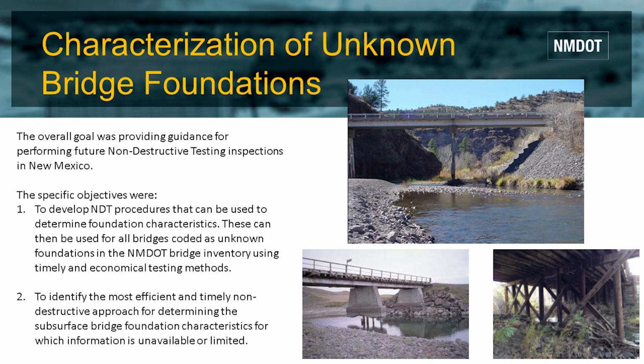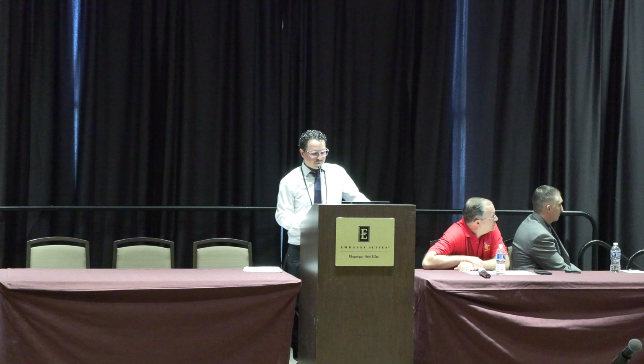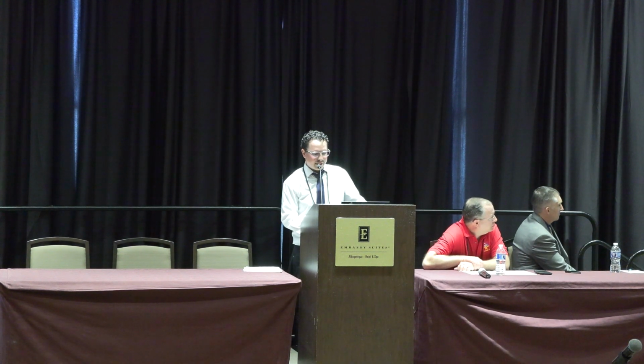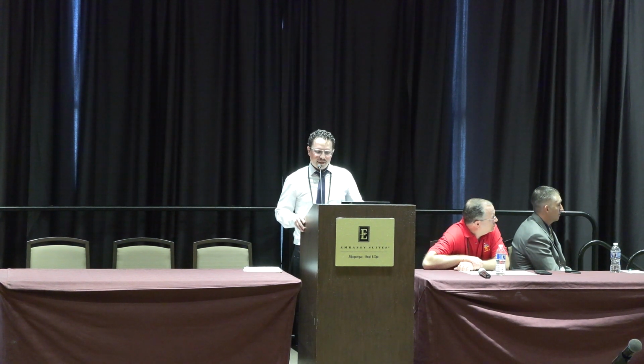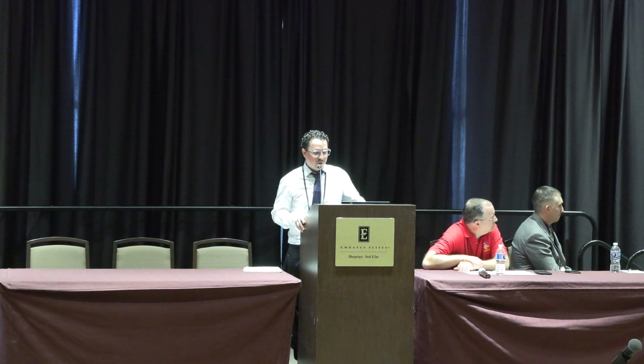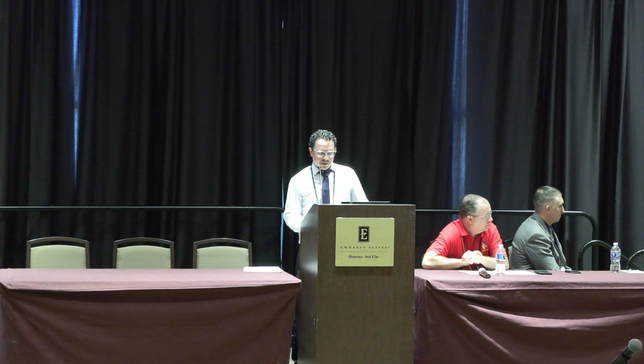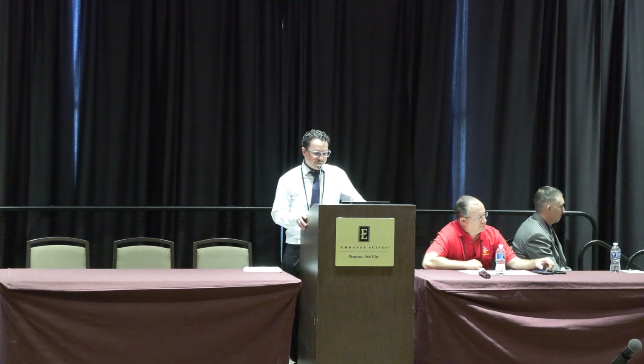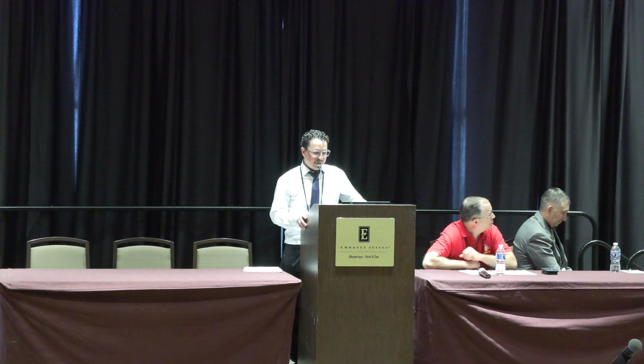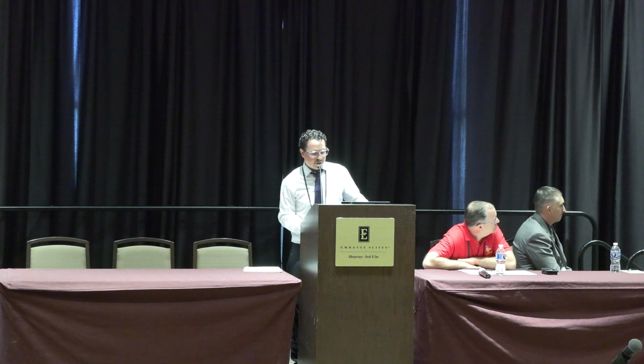The goal of this research was to determine the characteristics of unknown bridge foundations, such as type, depth, geometry, and materials. Field tests of local practice were first conducted on New Mexico bridges to determine the depth of the foundations. Test procedures of non-destructive testing methods were developed and helped NMDOT engineers to characterize unknown bridge foundations. The study showed that the reliability of locating the depth of the pile decreased as the distance between the borehole and the pile increased. The test methods that were created were both done in the laboratory and in the field. NMDOT engineers can follow these procedures and perform non-destructive tests to characterize unknown bridge foundations.